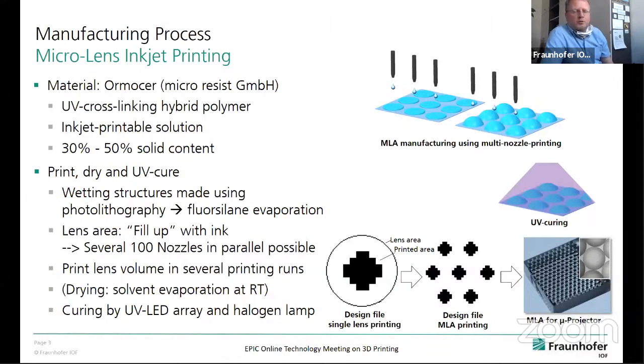Of course, we do that in several runs. Sometimes you have even up to 1,000 droplets in one microlens. The big advantage of the printing process is you can really individually address each lens itself. That is the big difference to replication processes where you have a predefined radius of curvature of the lens by means of your master. With inkjet printing, you can really individually address the radius of curvature of the lens simply by changing the dispensed volume on the pre-patterned surface.